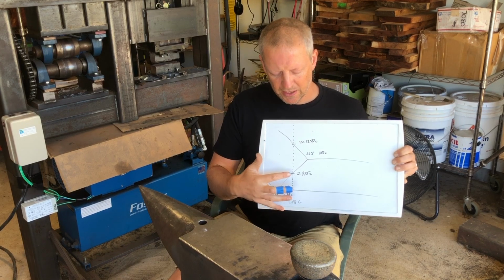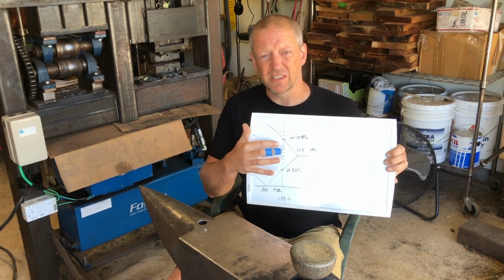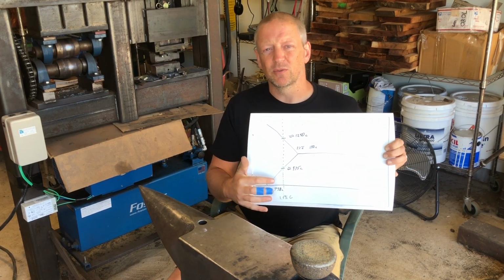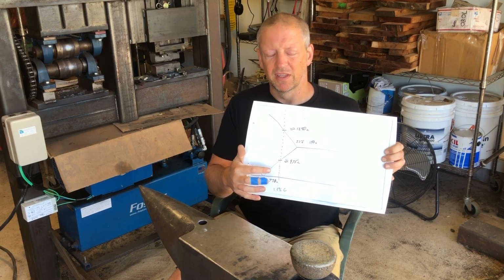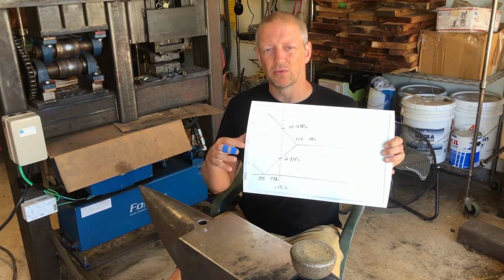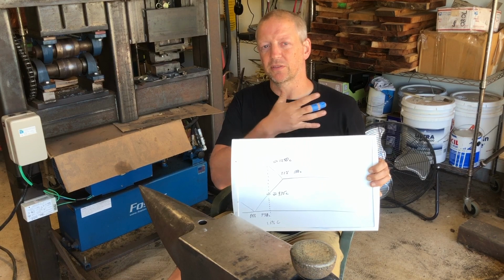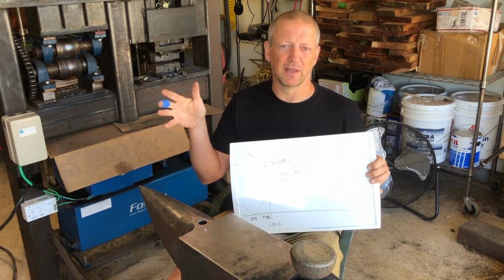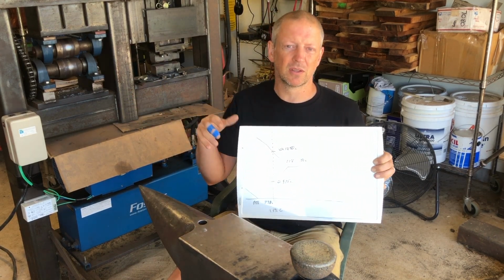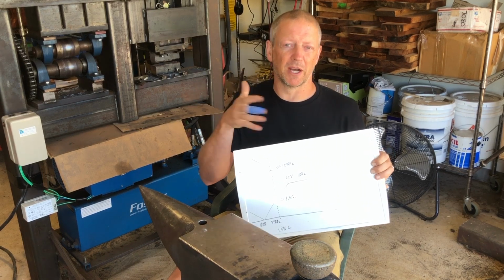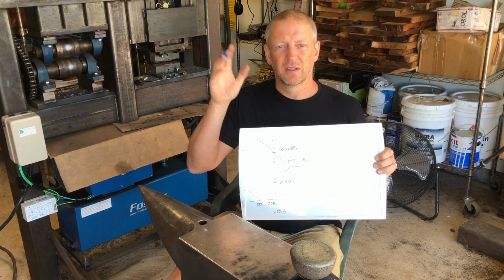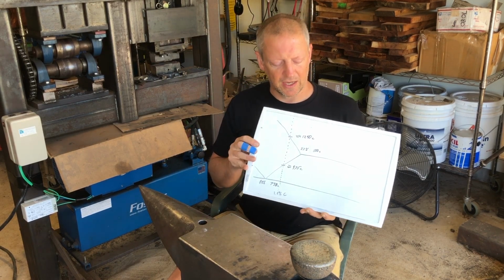So if we're at 1250 C, we're clearly well above the ACM. And that means that a long roast at that temperature, you will diffuse your carbon completely. You will have no remnant structure or remnant carbides from the initial solidification and cooling.